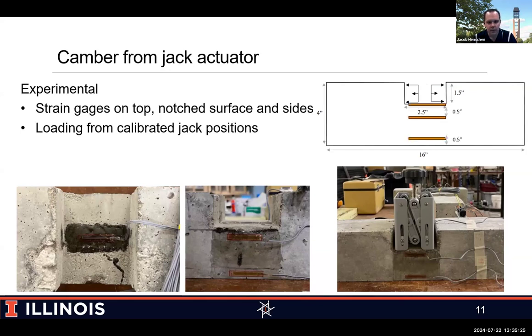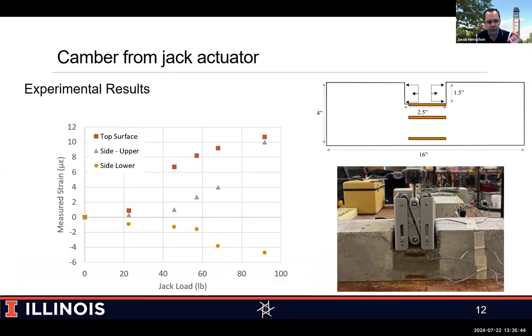So then what does the experiment look like? Using that jack, we were able to apply the load basically up and down, and we did that several times within that calibrated spot between 0 and 90 pounds. And this is what the results showed: we see what we expect. There's probably some seating loads or seating behavior within the jack, so we maybe don't see the nice linear trend that we would expect.